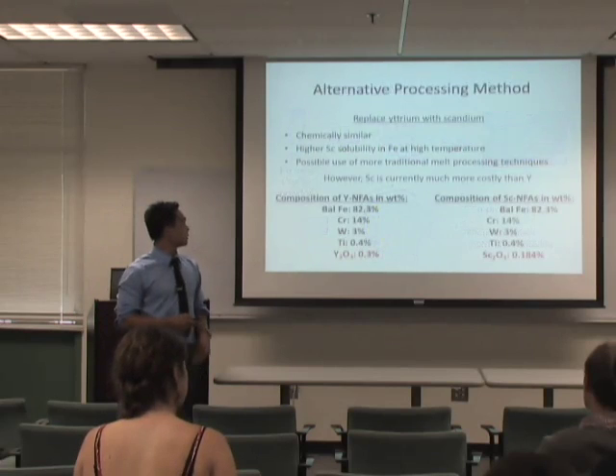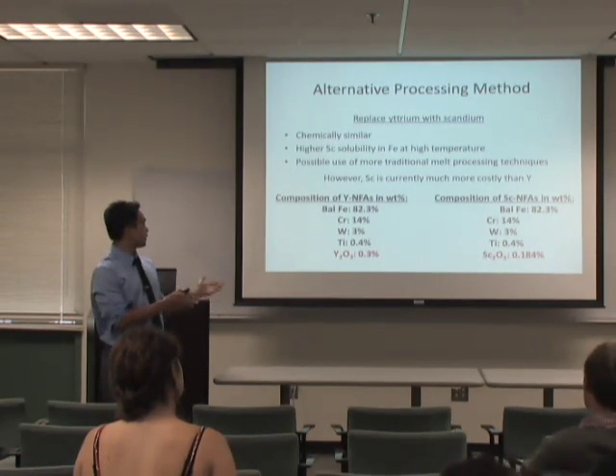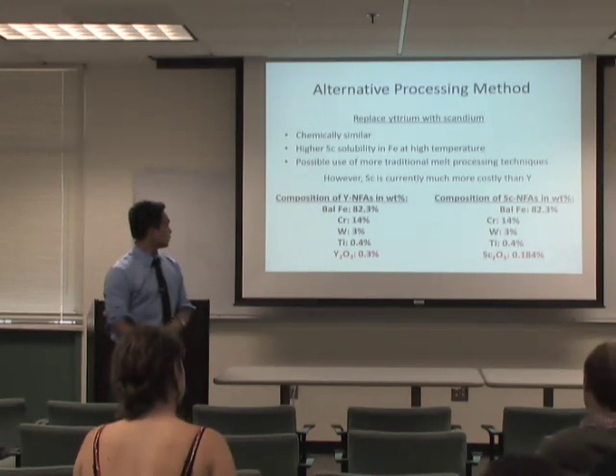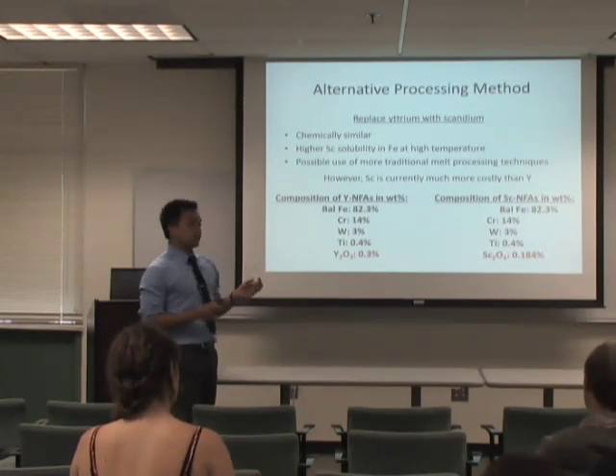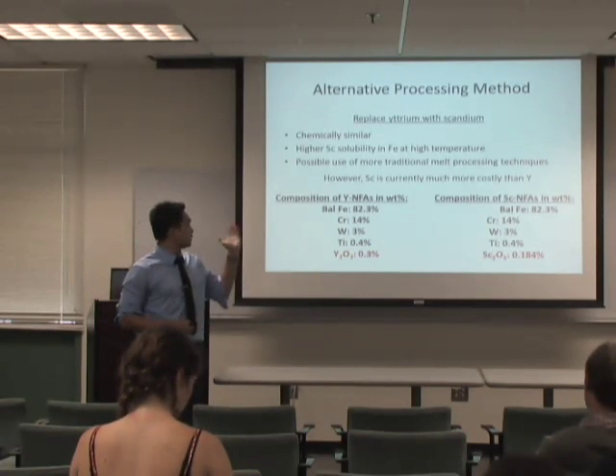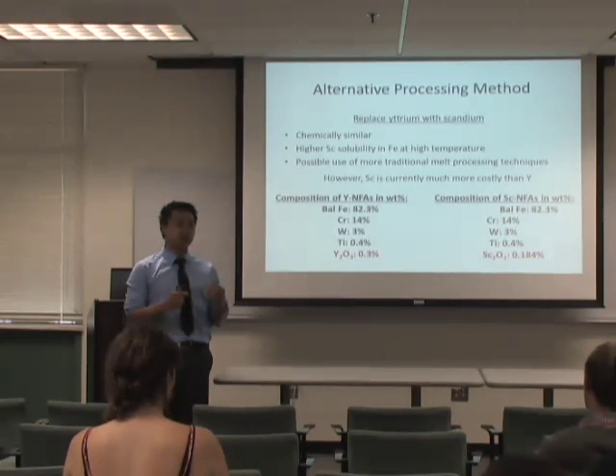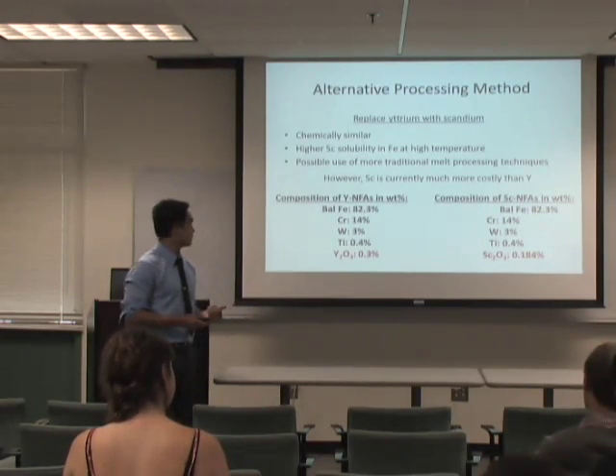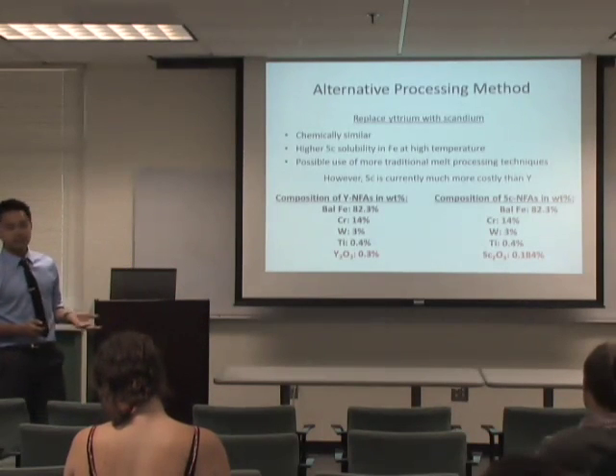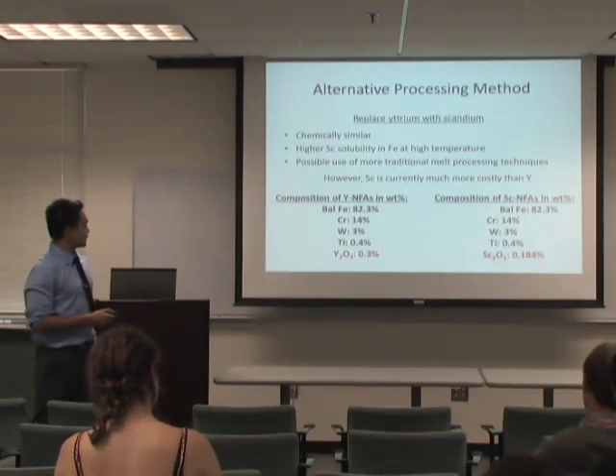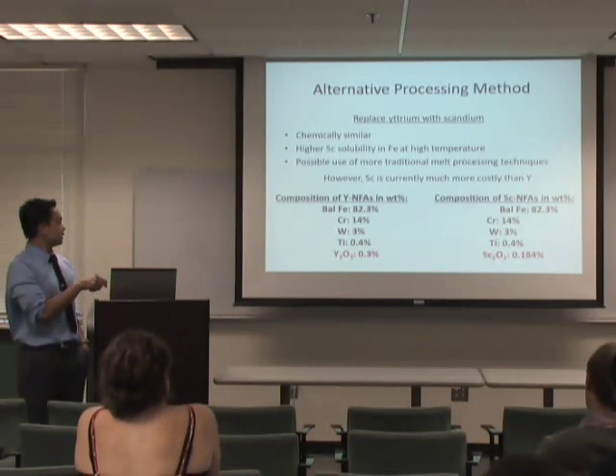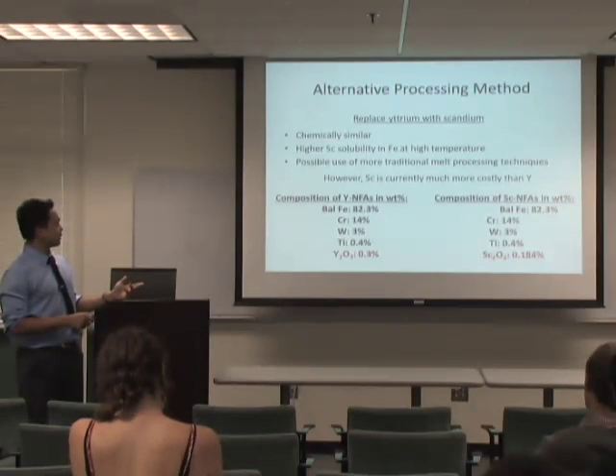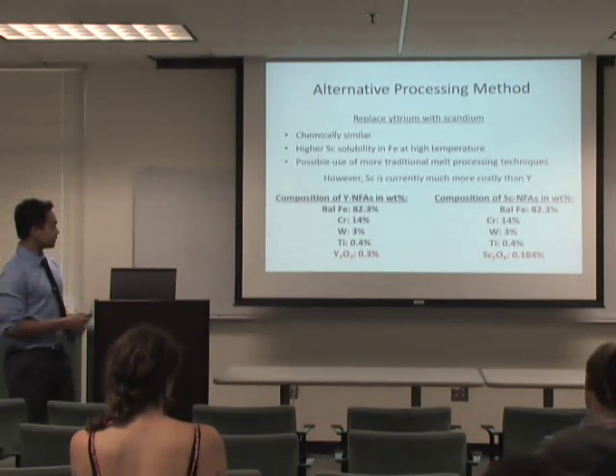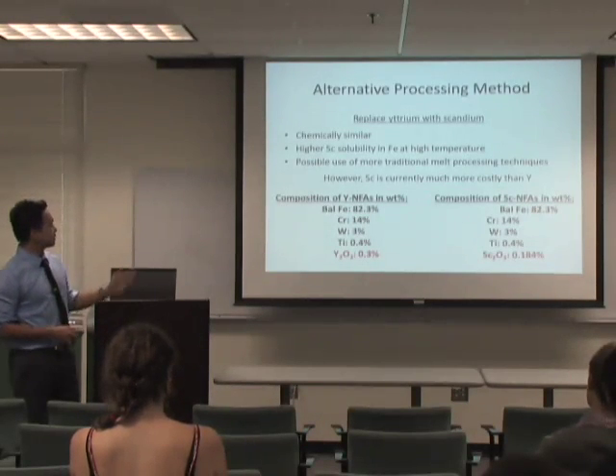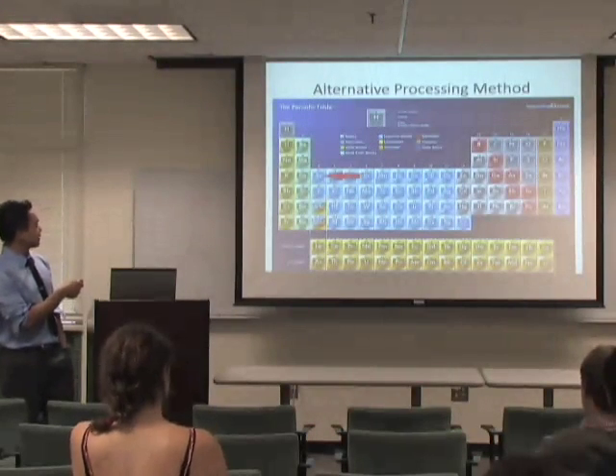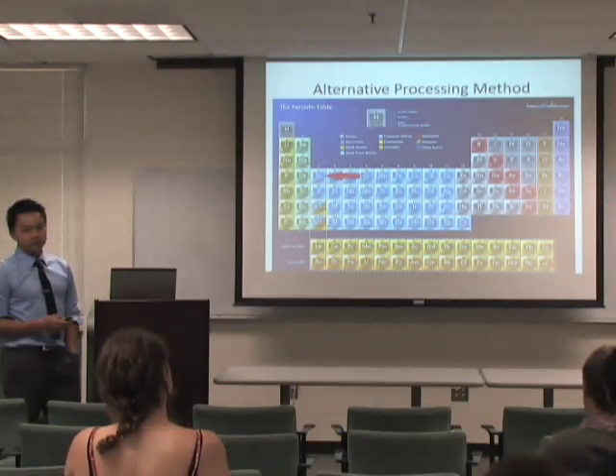And to do so, our group hypothesized that we can replace yttrium with scandium, another group 3 element in the periodic table. And we can do so because they're chemically similar. Scandium is much more soluble in iron than yttrium. And because of this, we can eliminate mechanical alloying and proceed with traditional melt processing techniques. Now, one of the drawbacks of scandium is that it's currently more expensive than yttrium. And in terms of composition, I have converted the atomic weight of yttrium and scandium to weight percent. So as I've shown here, here are the compositions of the 2 NFAs. And on the periodic table, scandium sits nicely on top of yttrium, making a very nice candidate to explore.